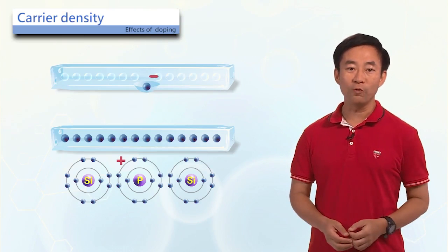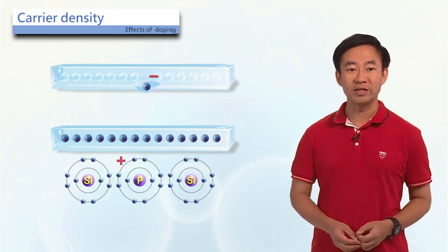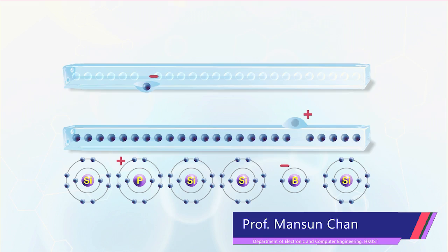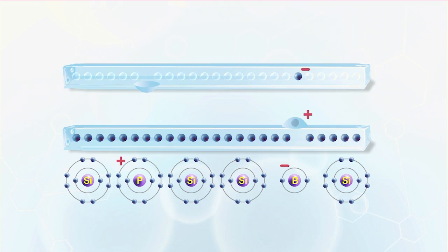What happens when you add both donors and acceptors to a piece of silicon together? When an electron moves to a place where there is a hole, the electron may take its position. The process is known as recombination. At the site of a donor atom, a positive charge is left behind at the atom core after the electron moves away. At the location of an acceptor atom, the core atom becomes negatively charged after the state represented by a hole is taken up by an electron.